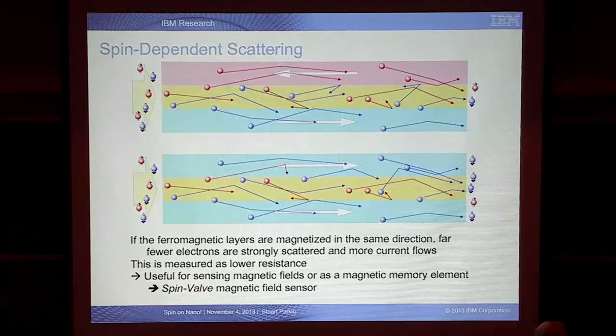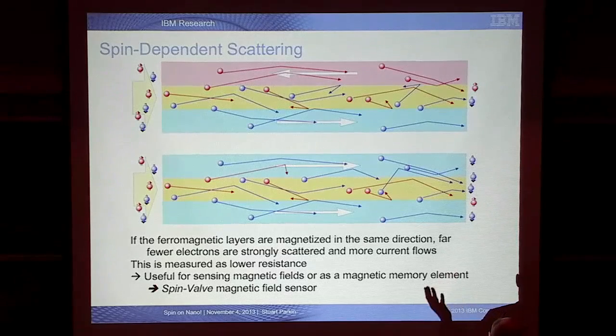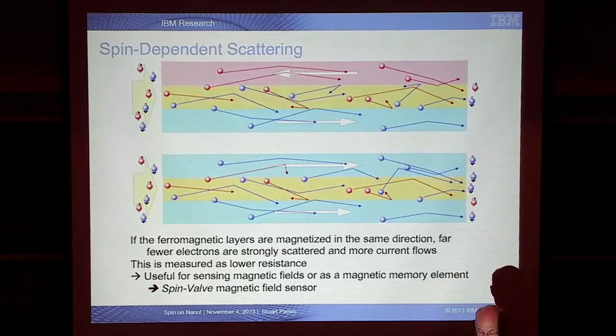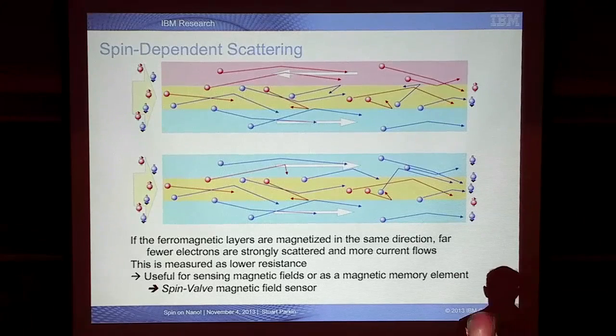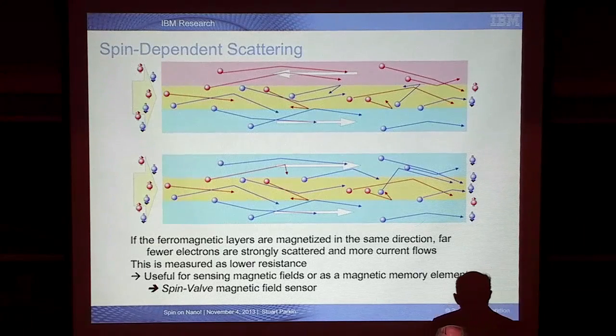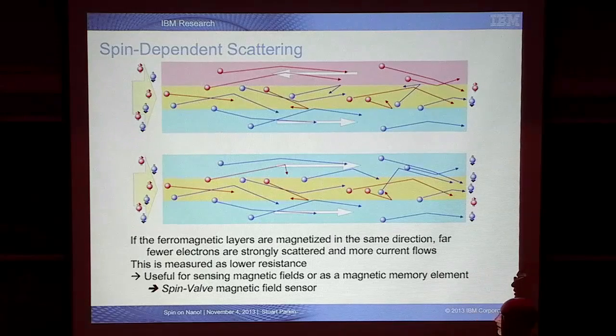If you have this sandwich of two magnetic layers, when their moments are antiparallel, because the electrons essentially see these layers through this intermediate layer through which they can be transported, the resistance is high. And if we apply a magnetic field, so the moments want to be parallel to the field, just like two compass needles, they will want to be parallel to the magnetic field we apply. In that case, the resistance will be lowered. So essentially, this is a valve for spin-polarized electrons. Very simple concept, but it turns out this simple concept enables us to build a device that can sense the magnetic field much more sensitively than any other device.